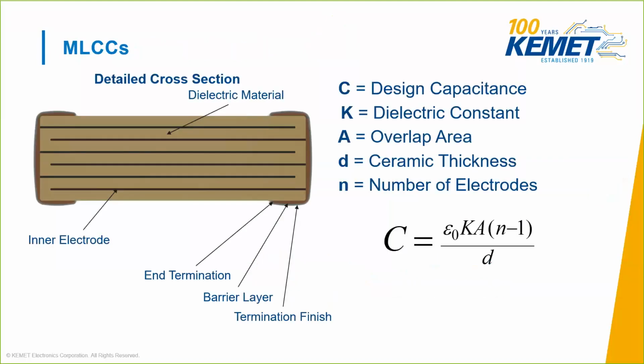Okay, so before we go into detail on high voltage, let's review basic MLCC design. Now, MLCCs are constructed using alternating layers of ceramic dielectric with metal electrodes. Each layer represents a single capacitor, and adding additional layers adds more capacitance to the MLCC since they are in parallel. We calculate capacitance using the capacitance equation as we can see in the slide. Now, by looking at the parameters, if we increase the dielectric constant, the area of the electrodes, or the number of layers in the capacitor, we will increase the capacitance. We can also choose to reduce the dielectric thickness since the capacitance is inversely proportional to the thickness. Now, if you were to reduce the ceramic thickness in half, it would theoretically double your capacitance because you could put more layers in the MLCC structure.